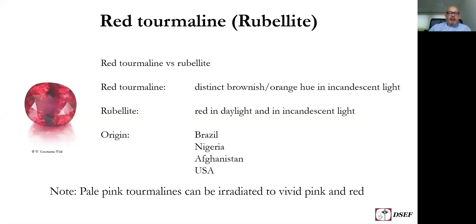Note that many red tourmalines are irradiated. Normally, they are pale pink before irradiation, and then the stones are heat treated, then they become colorless, and then they are irradiated, and this irradiation oxidizes manganese, and then the stone becomes bright pink. However, also the natural pink tourmaline is colored by manganese 3+, which is actually a result of natural ionizing radiation. So unfortunately, we cannot distinguish between artificially irradiated and naturally irradiated red or pink tourmaline.